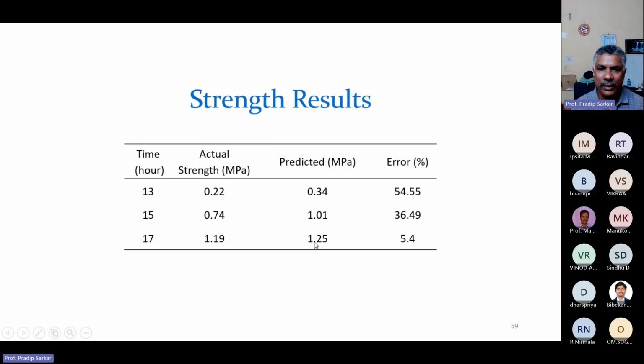So we saw in the very early age, 13 hours, the deviation is a little high, but as age increases in terms of hours, at 17 hours the error is very small, and the values are not very different.